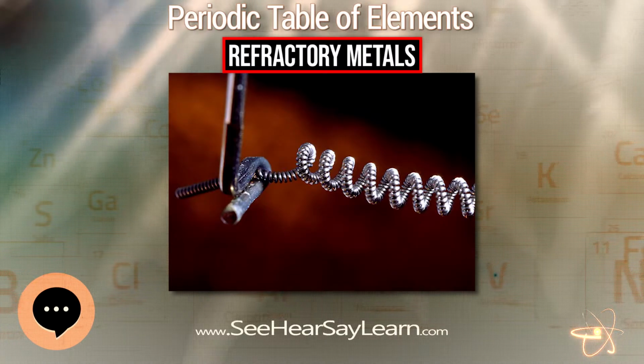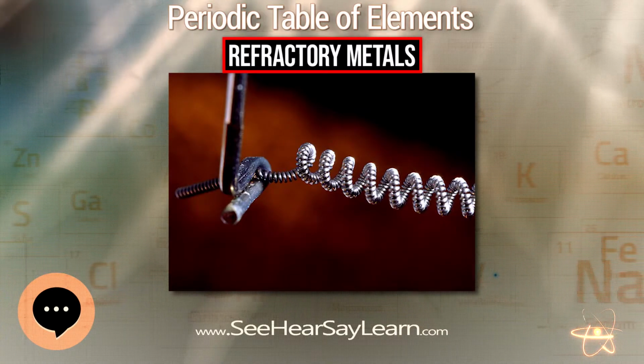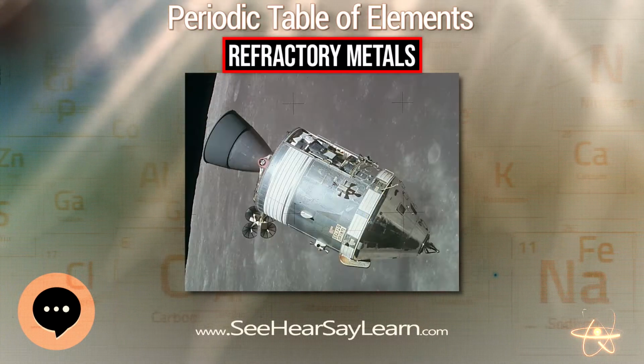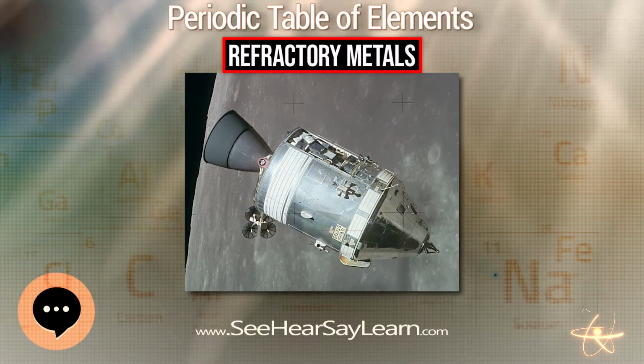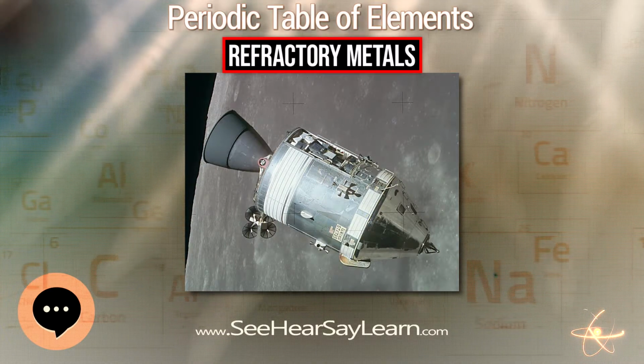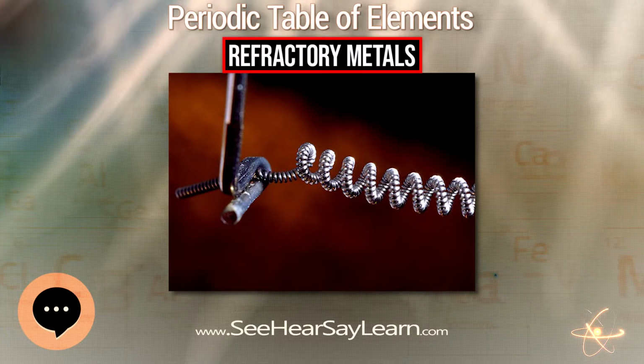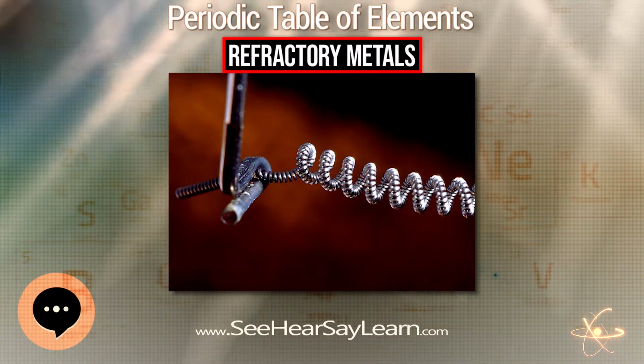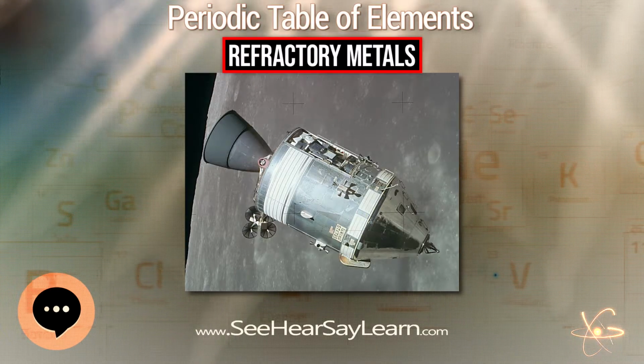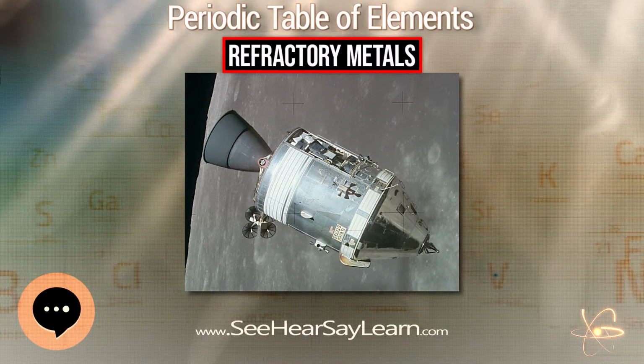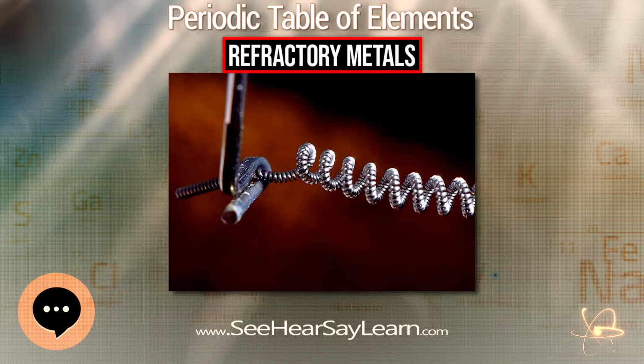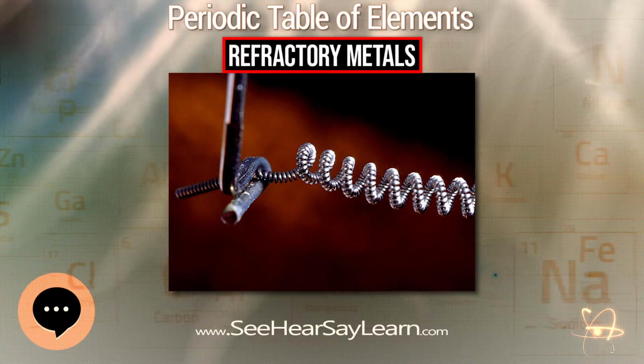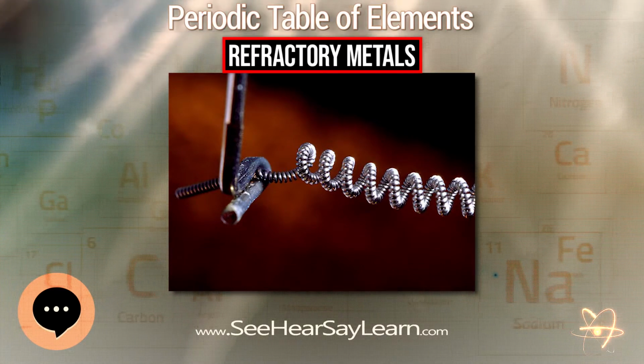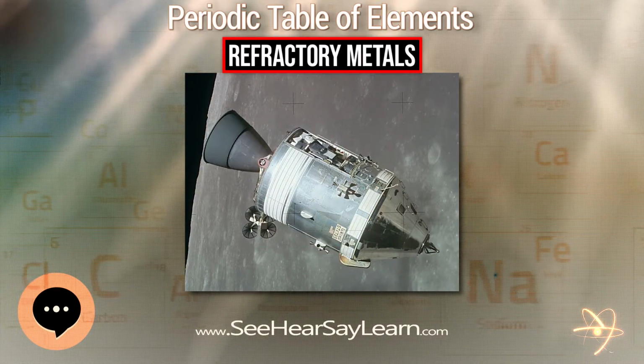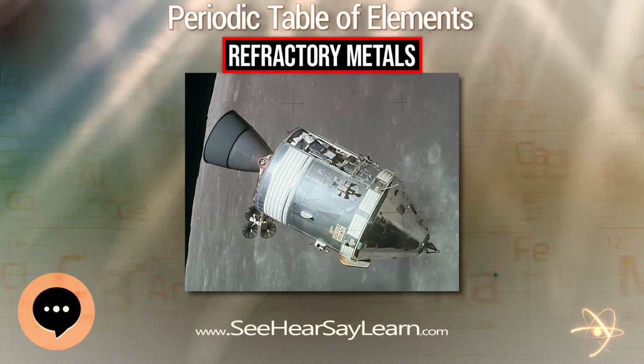An alloy used for liquid rocket thruster nozzles, such as in the main engine of the Apollo lunar modules, is C103, which consists of 89% niobium, 10% hafnium, and 1% titanium. Another niobium alloy was used for the nozzle of the Apollo service module. As niobium is oxidized at temperatures above 400 degrees C, a protective coating is necessary for these applications to prevent the alloy from becoming brittle.